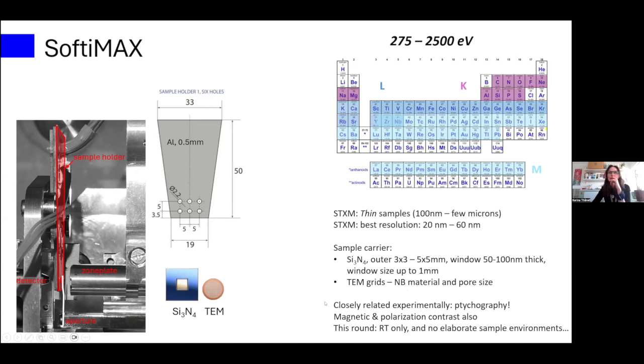What we can also do at the beamline is ptychography. It's a somewhat related technique, which I'm not going to go into, but it is generally for samples that are scattering. So it is very heavily used in magnetism, but anything that is a little bit more, not very smooshy, let's say. It can help with increasing the resolution, but it comes with the cost of being slightly more difficult with the data analysis. We also have the possibility to work with magnetic and polarization contrast in your samples by changing the polarization of the light that we have, so the polarization of the photons, if that is something that you would need.